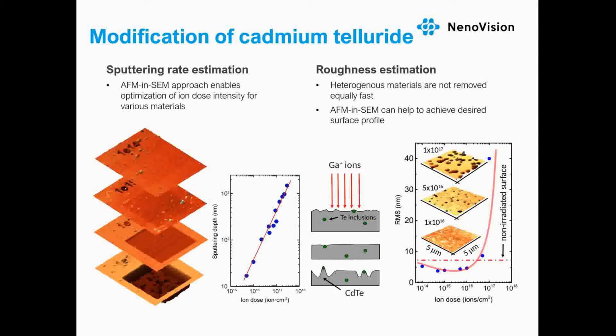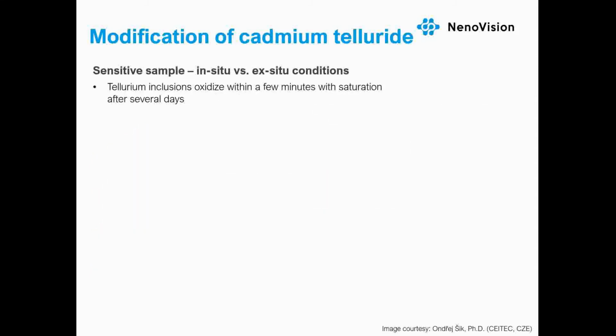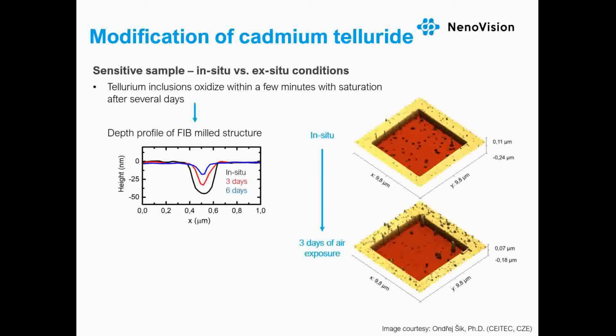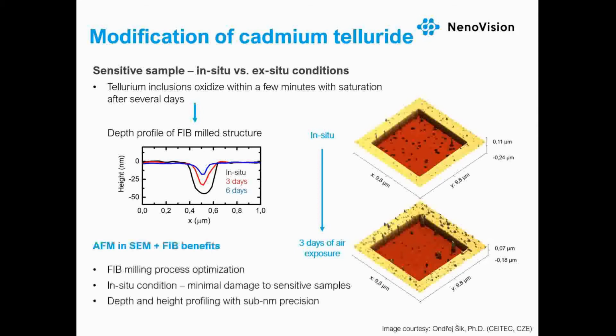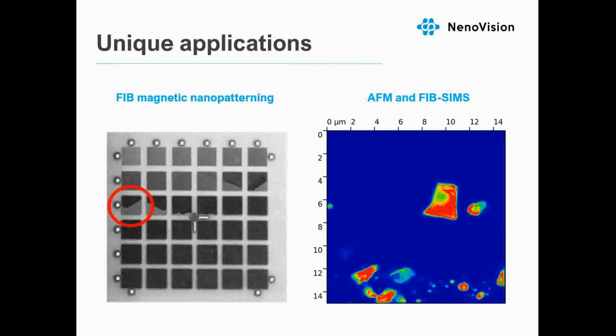Cadmium telluride represents a sensitive sample, and an AFM analysis of one of the FIB milled structures demonstrates the importance of in-situ conditions. Both the AFM topography and the measured depth profile show the sample oxidation over time when exposed to atmospheric conditions. According to this analysis, tellurium inclusions oxidized within a few minutes with saturation after several days. Towards the end of this presentation, I will show two applications where the focused ion beam wasn't used primarily for material microstructuring, but rather as an analytical probe.